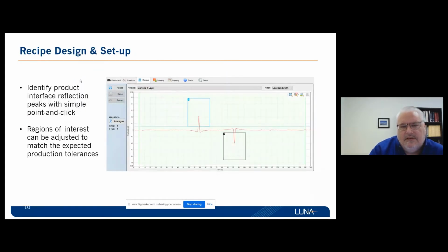This is just a screen showing what the instrument does in sort of an intermediate processing level, where you would get, say, one reflection pulse and a second reflection pulse, and we're setting up a recipe to calculate the time of flight between those two, so you can calculate the thickness, say, of this material.